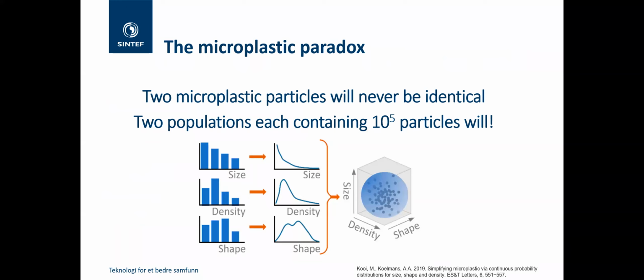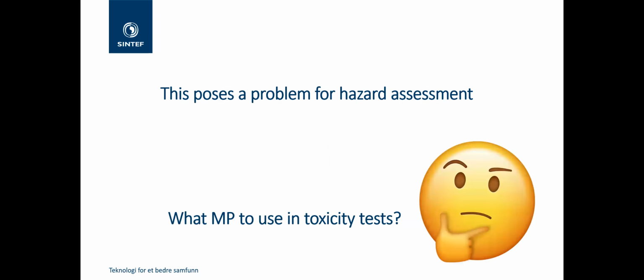And because of this fragmentation, there was a nice study by Bart Koelmans' group in the Netherlands a couple of years ago. They basically demonstrated that no two microplastic particles would ever be identical. You need two populations that would each contain 10 to the 5 particles to get an average set of properties that would be the same. So that's the kind of complexity we're dealing with in this particular form of pollutant, and it's quite a long way away from individual chemicals or metals as pollutants. It really represents a sort of complex mixture of particulate and chemical pollutant. And it's this that poses a problem when it comes to hazard assessment. What microplastics, what test materials should we use in toxicity tests?